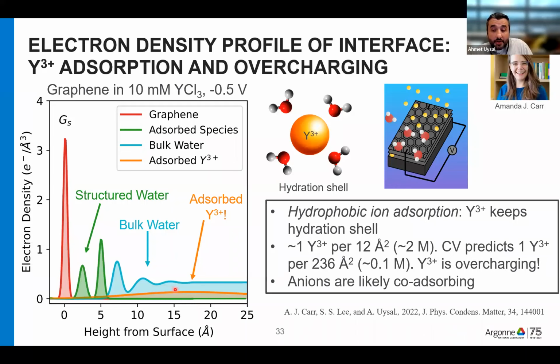And the other interesting thing is the concentration of yttrium is significantly higher than what you could estimate from a cyclic voltammetry measurement, for example. A CV measurement would tell you the interfacial concentration of yttrium is around 0.1 molar. Remember, our bulk concentration is 10 millimolar. So this is already a high concentration compared to bulk, estimated from CV. But our RAXR measurements are actually saying that we have 20 times more yttrium close to the interface than we could estimate from the CV measurements.